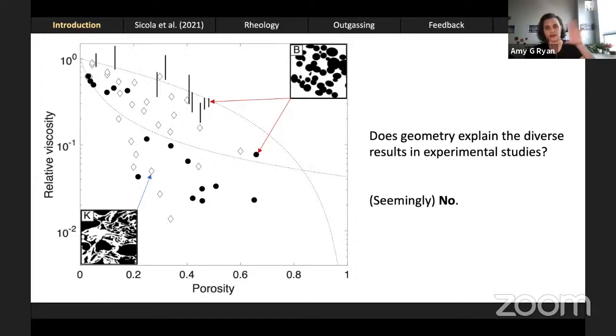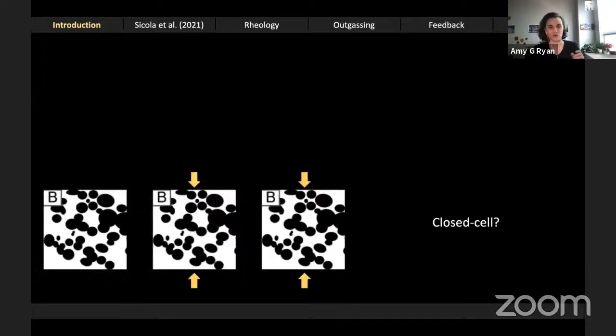So I've sort of colored or coded this to reflect the different geometries. The open diamonds are more like this material K, and the black circles are more like material B. And what you see is that the separation by geometry doesn't quite answer why we have such a diverse range of results. Part of that, I would say, is because of a flaw in the way I've set up this thought experiment for you, which is equating this bubble geometry with inherently being closed cell. And I'll show you why that's a problem now.